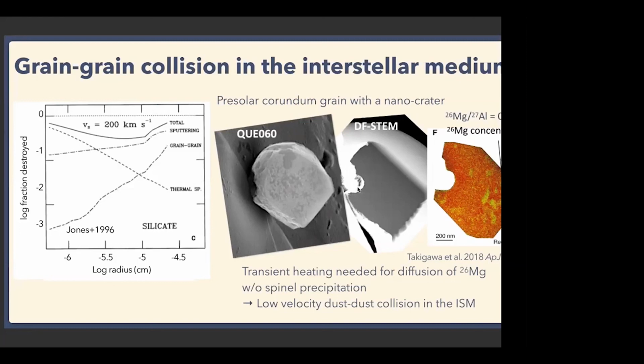This grain also has some features that may indicate it experienced transient heating, because some magnesium concentrates in small regions, and these magnesium concentrated regions are probably related to this cavity formation. So in this case, the energy was probably less than the critical energy that would shatter this grain, and just a small crater remained on the surface. So probably we can find more signatures of grain-grain collisions if we analyze each presolar grain in detail.